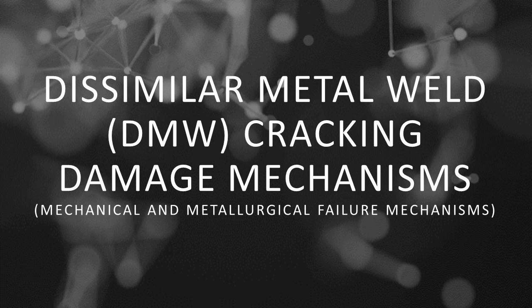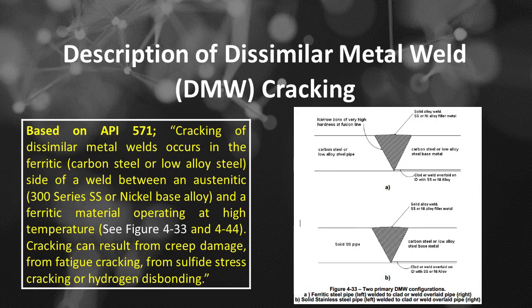Dissimilar metal weld, or DMW, cracking damage mechanisms is a part of mechanical and metallurgical failure mechanisms. Description of dissimilar metal weld, or DMW, cracking based on API 571. Cracking of dissimilar metal welds occurs in the ferritic, carbon steel or low alloy steel, side of a weld between an austenitic, 300 series SS or nickel base alloy, and a ferritic material operating at high temperature. Cracking can result from creep damage, from fatigue cracking, from sulfide stress cracking or hydrogen disbonding.